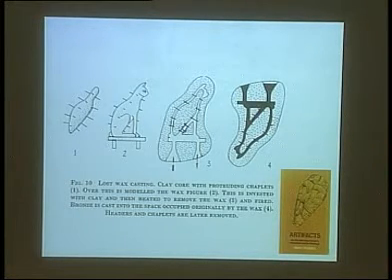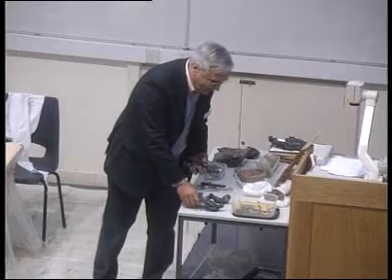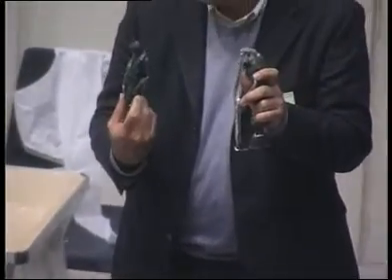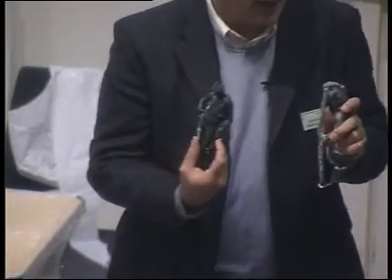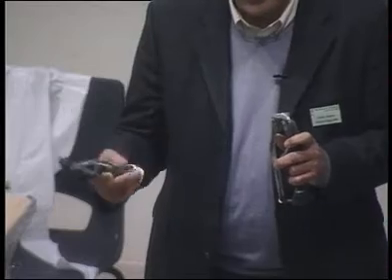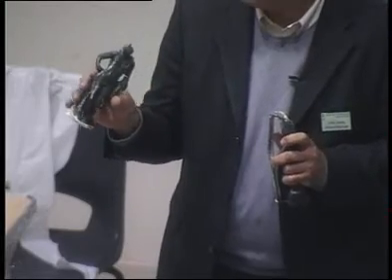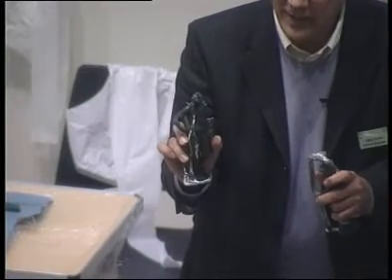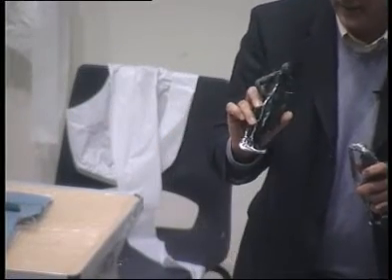From our teaching collection, I've brought along some examples. Right now I happen to be interested in Renaissance bronzes, so I have to maybe make a cat. That's the next step. These are some models of different examples of lost wax casting, where with direct modeling, the object, the cat in this case, can be made in wax with or without a core. These little pins that you see going into the side, those are very characteristic, again, for holding the core in place.